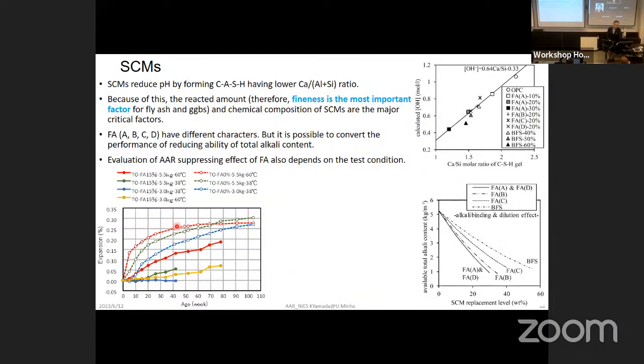But if it is a thin material, really a powder lower than 50 microns, like the size of the cement. Yes, but please imagine. There is silica and sodium. If sodium is added into concrete, what happens? More reaction. But if silica is added, silica reduces the calcium silicon ratio. So we have both effects simultaneously. So which effect is more or less? So that's a balance. This powder is too small, so it cannot expand by itself. But this powder can affect the pore solution composition.